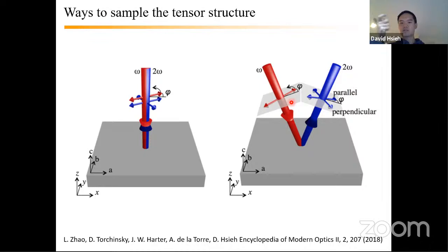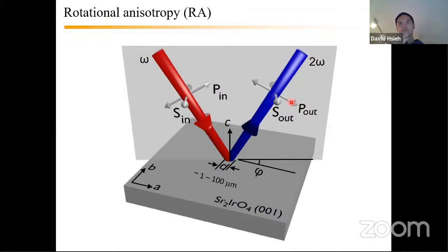And so really I think the more exhaustive but more complicated setup is one where you perform what we call a rotational anisotropy measurement, where you're coming in with oblique incidence, but you're also rotating the scattering plane relative to the sample normal, okay, about the sample normal. And so if you adopt this geometry and you acquire SHG intensities as a function of this angle phi about which your scattering plane rotates about the surface normal, and you do these experiments with different ingoing and outgoing polarizations, that's a pretty exhaustive way of mapping out this tensor structure, okay, being sensitive to all the tensors in your response.